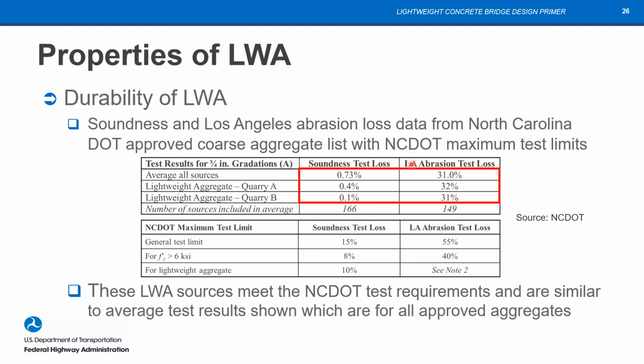Same thing with LA abrasion, where you would think that this porous rock would suffer badly in the LA abrasion test. The average for all rock was 31%, and these two are 31 and 32%. So they're well below the limits that are given for NCDOT. So what I like to recommend is that if you have requirements for normal weight aggregate, the lightweight aggregate should be required to meet those if at all possible, and here it demonstrates that you certainly can. One thing to note is that the test method needs to be adjusted a little bit for using the LA abrasion test, because you end up packing the drum with more aggregate than you would have for normal weight aggregate, so it doesn't fall as much. So you should use an equivalent volume, not an equivalent mass.